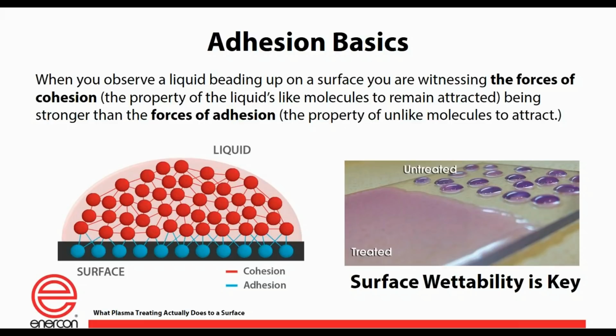It's also interesting to note that you can tell the difference in the height of the treated surface versus the untreated surface. And by that I mean the amount of material it would take. You can easily see that on the right, I would have to completely cover that surface with adhesive in this case, and my level there would be much higher than the treated surface where I'm getting good wettability. What that basically means is if I'm using adhesive in this situation, I'm using more adhesive.